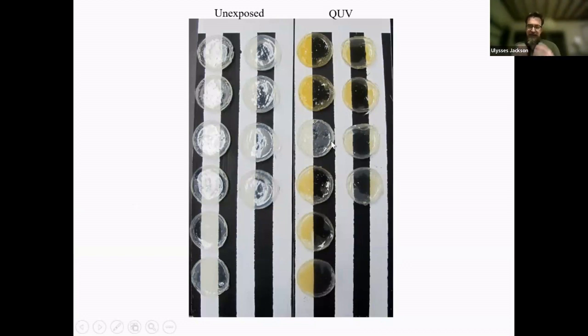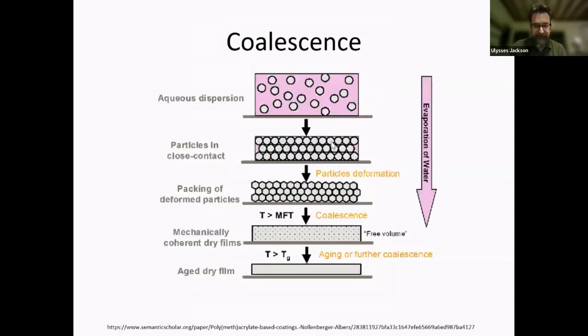So we start with a binder because it's going to give you the gloss of your paint. It's going to really control the hardness, the flexibility, chemical resistance, all of those aspects. And because of that hardness, we have to think about the coalescence of the film, right? Sometimes we'll use a binder whose transition temperature is above the room temperature in which it's going to be curing. Those polymer spheres are floating around in that aqueous dispersion. The water leaves, they kind of cluster together. Then they start to slowly deform as if they're like soccer balls deflating into a honeycomb shape. Finally, those edges kind of diffuse, giving you that quote unquote dry film, or the first stages of dry film.